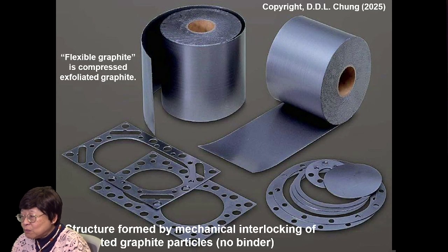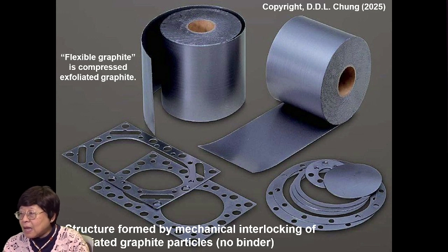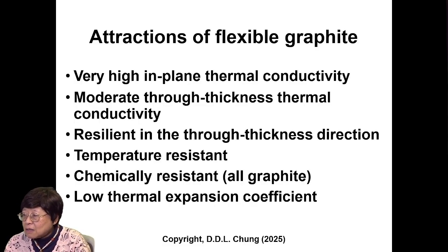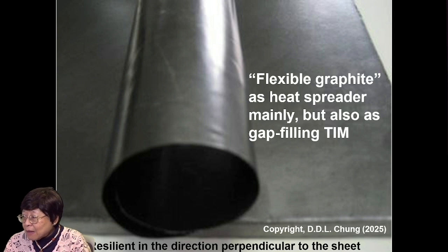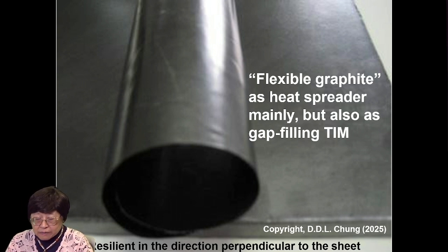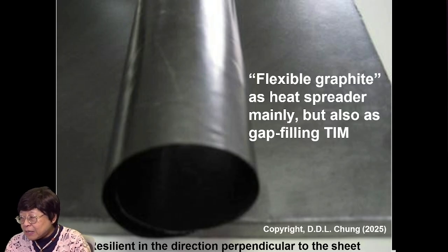When you have a pile of these worms, you can compact that in the absence of a binder. Due to the cellular structure, you have mechanical interlocking, thus resulting in a sheet called flexible graphite. The attractions of this sheet include these: very high in-plane thermal conductivity, moderate through-thickness thermal conductivity, resilience in the through-thickness direction, and temperature resistant, chemically resistant, since this is all graphite, and low in thermal expansion coefficient. Flexible graphite is widely used as a heat spreader because of the high in-plane thermal conductivity, but it is also used as a gap-filling TIM.